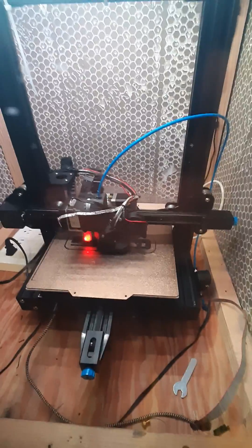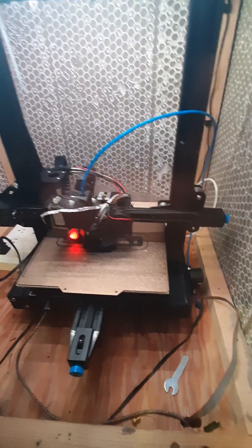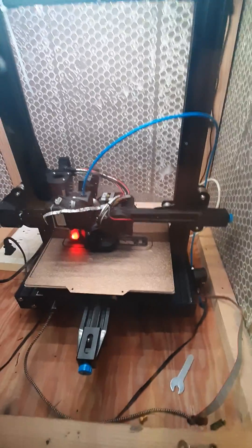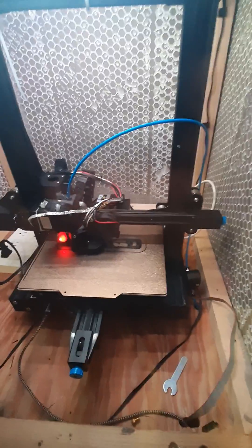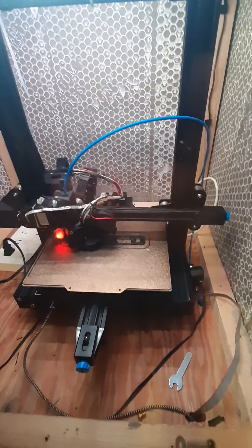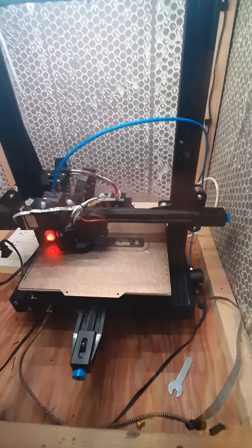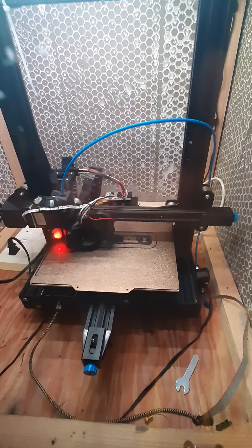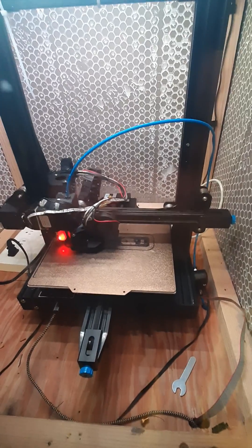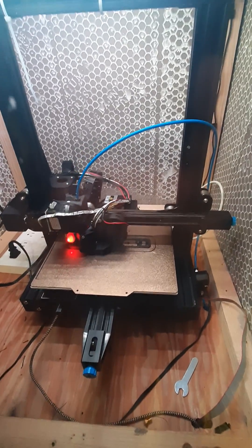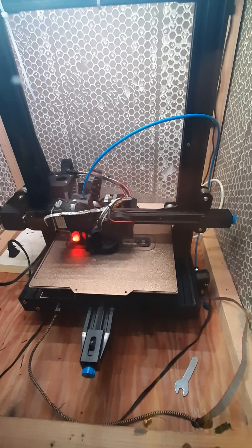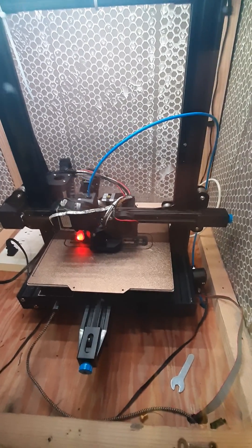I actually started printing some temperature samples and breaking them and I found that the closer you get to about 300, it's actually a lot better.